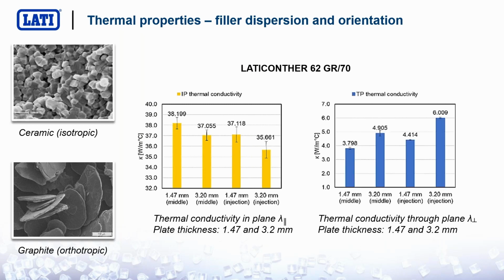Through plane is completely different. The conductivity through plane, which is normally the conductivity that is used in many applications, is much lower, and it is in the range from, I would say, 3 to 5 watt/meter Kelvin, up to 6, and it will be higher the higher the wall thickness.